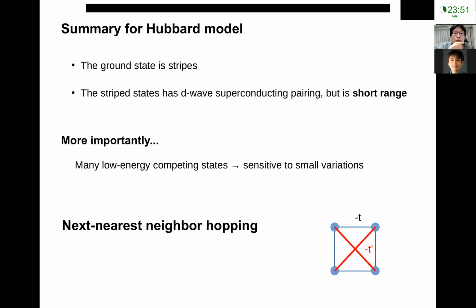To give a brief summary about the Hubbard model: the ground state is a stripe state, and the stripe has D-wave symmetry, but the pairing is only short range, so it's not really a superconducting state. But more importantly, we found many low energy competing states, which means the ground state of the Hubbard model is kind of sensitive.